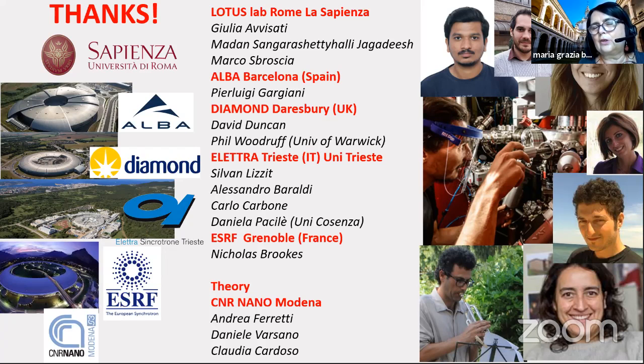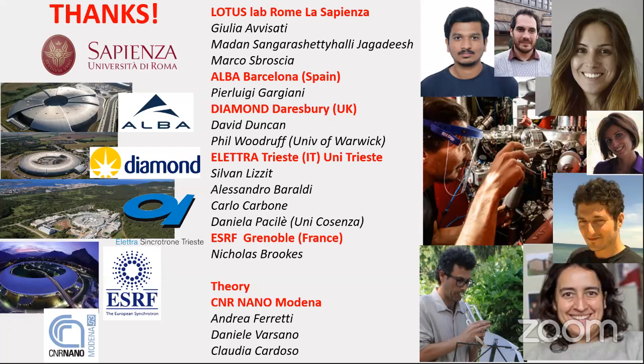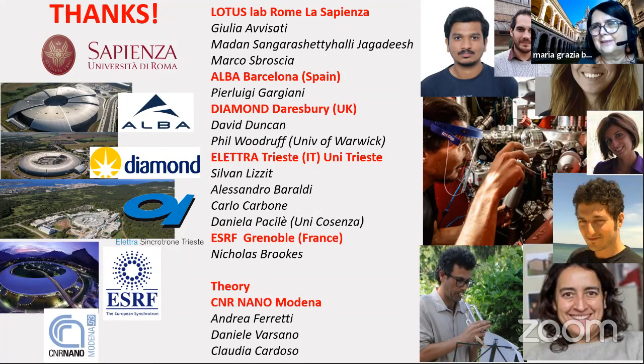And then comparing this with XMCD, and then with the switching of the magnetic states, we can confirm. And also we were measuring the work function of the system, to have a different calibration of the number of potassium atoms on the surface. So this is an important question. It's not so easy. Okay, so you have to compare with the XMCD.